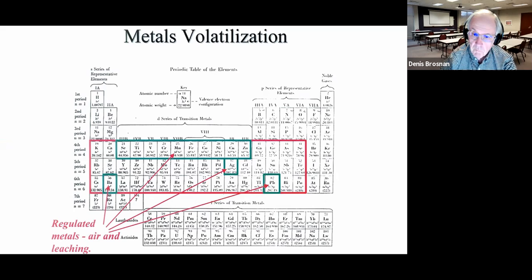So I've done some work trying to verify that in some very exotic instruments in Europe. And usually you have to be worried about metals vaporization at temperatures above 1250 degrees Celsius. You can at least begin to think about it. Now, it is true that in some operations, some refractory lined vessels like incinerators, if you have metallic chlorides, you'll get metals vaporizations at lower temperatures. Metal halides tend to have fairly high vaporization potential.